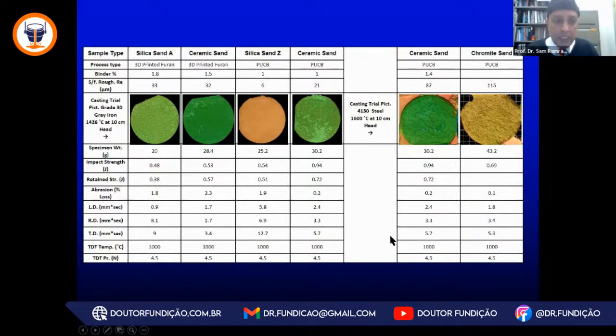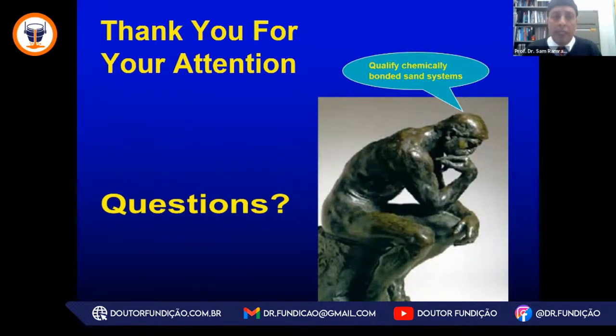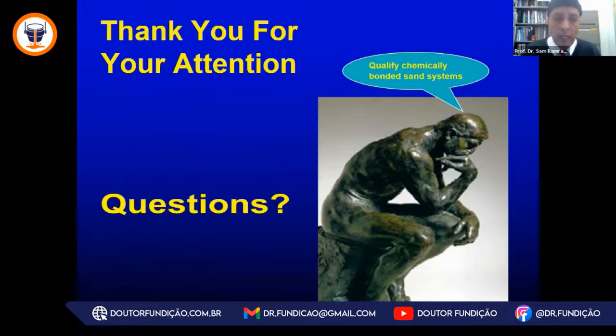But we are collecting a database for different binder systems, different interfacial conditions, and measuring the mechanical, thermal, physical, and chemical properties to develop the database for the sand binder systems, whether they be ceramic media, alternative media, or specialty media. We are trying to understand this from the sand binder system size, distribution, and variability relative to those conditions. The qualification is a performance predictor. We are seeing that it relates to actual production concerns. And for that reason, we encourage the foundries to qualify a chemically bonded sand system through testing and casting trials in order to prevent issues of defects and process concerns.